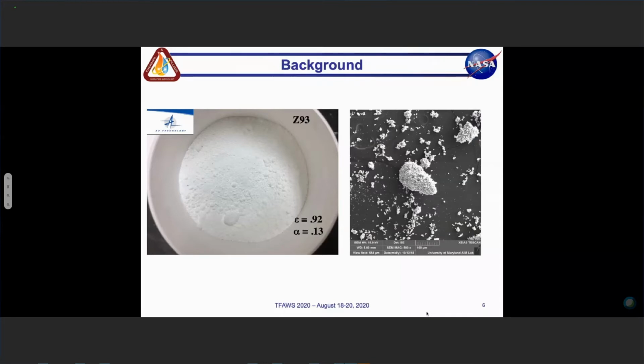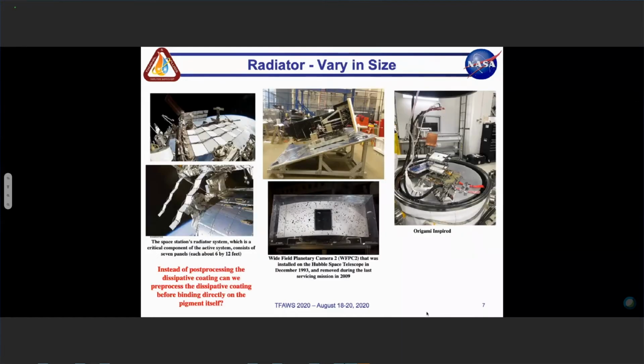But if we take a closer look at the coatings for these radiators, on the left is your typical Z93 coating, which has an emissivity of about 0.92 and absorptivity of about 0.13. This is from AZ Technologies. And if you look at a closer SEM image of one of these particular coatings, you can see that there is significant topography associated with these pigments. And what we want to do is take advantage of these significant topographies. The idea is that with this powder itself, we have a surface that we can dedicate and work on to meet some requirements we want in terms of charge distribution.